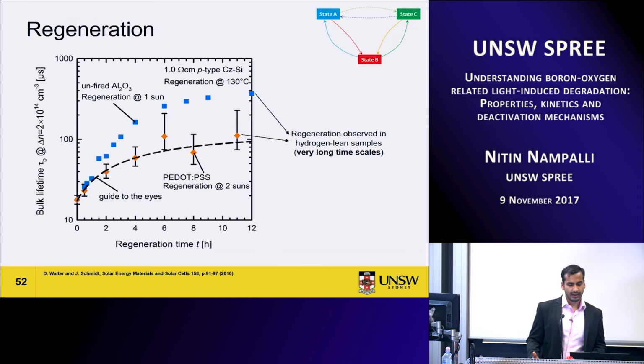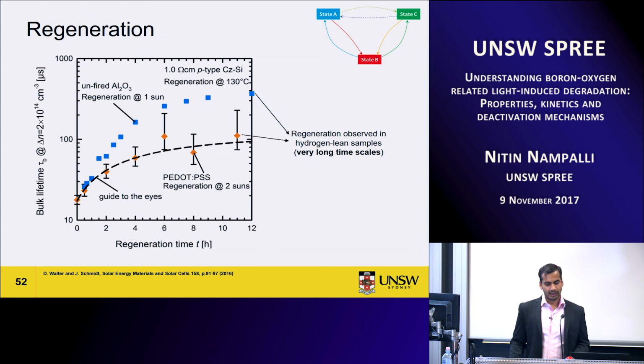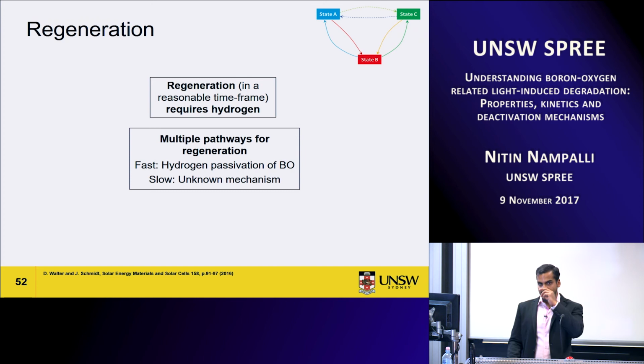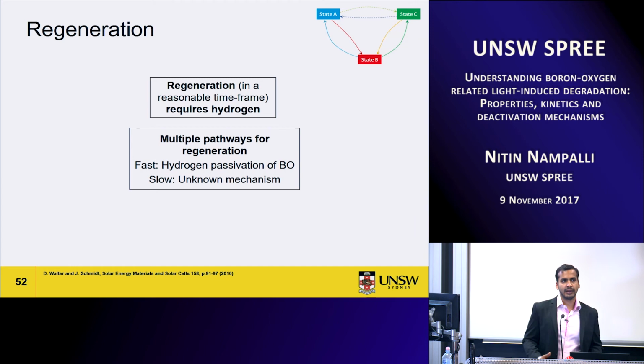So there's some doubt about whether hydrogen is directly responsible or whether there's multiple mechanisms. But what we can say is that regeneration in a reasonable time frame seems to require hydrogen. And there might, in fact, be multiple pathways within regeneration. One of them could be hydrogen-based. Another one, we don't know yet.